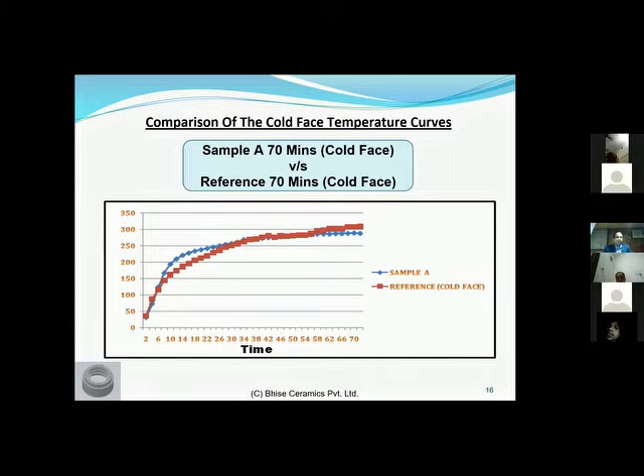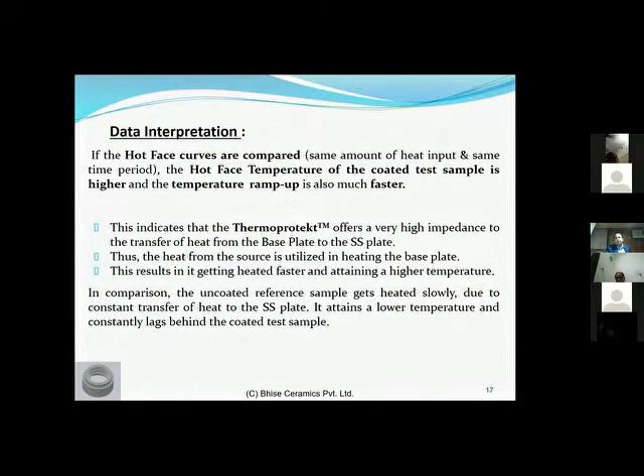Now if we had to summarize these observations, if the hot face curves are compared, with the same amount of heat input and the same time period, the hot face of the coated test sample is going at a higher temperature than your control sample, and the ramp up rate is much faster. This indicates that even the small layer is giving a very high impedance to the transfer of heat from the base plate to the SS plate. What it really means is, if you have a barrier over there, the heat actually does the work of warming up the plate and is not transferred to the substrate that is on top.